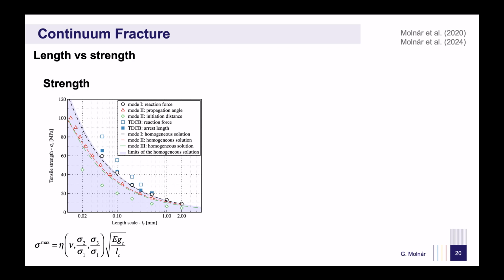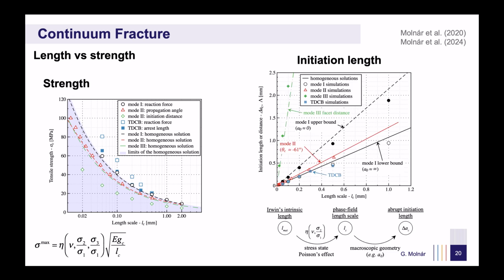When summarizing all our correlations, we see the same trend. As LC increases, tensile strength decreases. However, this relation is not a unique single curve, but rather a failure surface. This is confirmed by plotting the length scales derived from the coupled criteria, showing that all distances scale linearly with LC, but differ depending on the loading case. This leads to an important conclusion. LC is not the size of the process zone. While it influences the process zone, local instabilities depend on the specific fracture case.